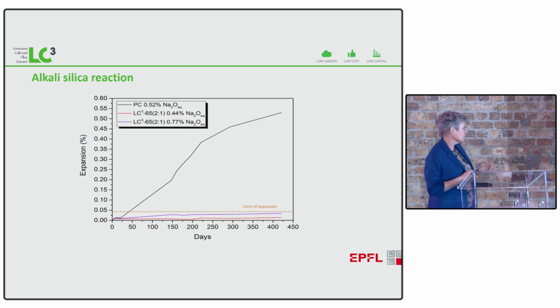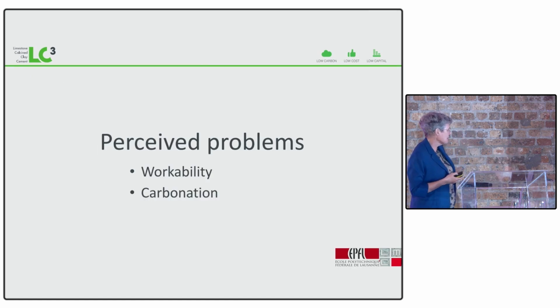These were some studies we did with the Thai group, SCG, and you can see even if you add in extra alkalis, they were producing a low alkali cement, which is actually quite wasteful in terms of CO2. But even if we increase the alkali content quite substantially, we still get absolutely no reaction in alkali silica.